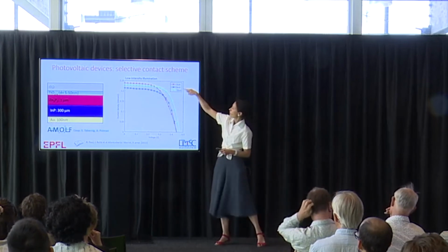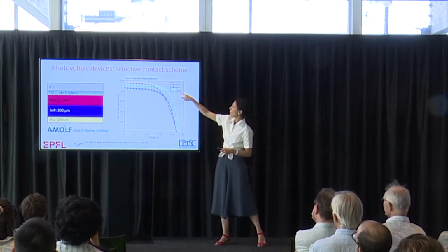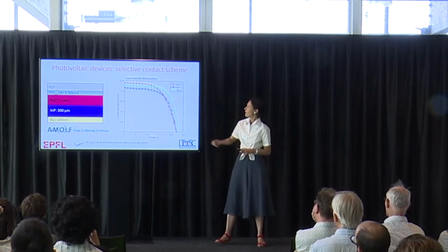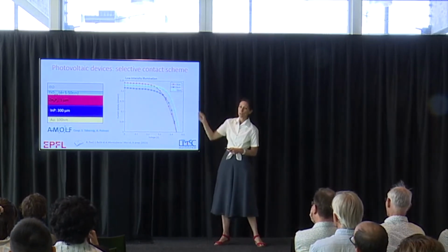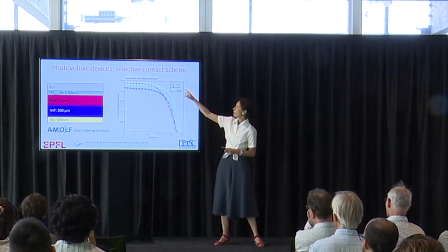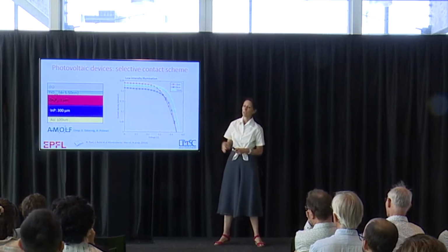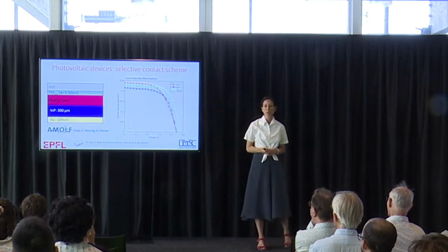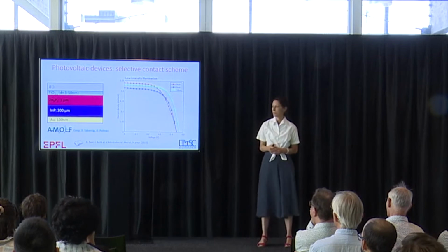Depending on the thickness of the TiO2, you see how you have an optimum at 10 nanometers, which makes sense. Below 5 nanometers, you don't have a continuous film. At more than 20 nanometers, it has to be more resistive, so it doesn't work. So 10 nanometers is the best.